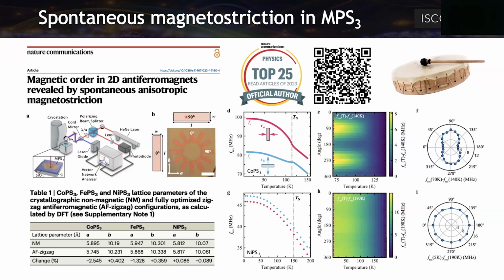And interestingly, they observed in the experiments that, for example, in the case of cobalt, when the temperature is decreasing, below the Néel temperature, going to low temperature, the material is compressed along the a-axis and is expanded along the b-axis. And when we have nickel, the effect is not happening. So with nickel, everything is isotropic here, but we have this peanut shape in the case of the iron and the cobalt, that in this case are experiments for the cobalt, that are a mark of this effect.